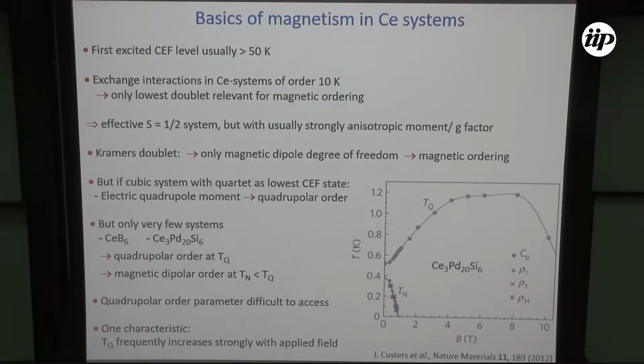Because it's a Kramers doublet, we have only a magnetic dipole degree of freedom, and therefore we have only magnetic ordering, or alternatively, if we have coupling with the conduction electrons, a Kondo screening. But if the system is cubic and the quartet is the ground state, then this quartet has an electrical quadrupole moment, which provides a further degree of freedom, and we may have quadrupolar order. The problem is that there are only very few such systems. There are quite a lot of cubic systems, but in most of them it's the Gamma 7 doublet which is the ground state, and therefore we have no quadrupolar order.